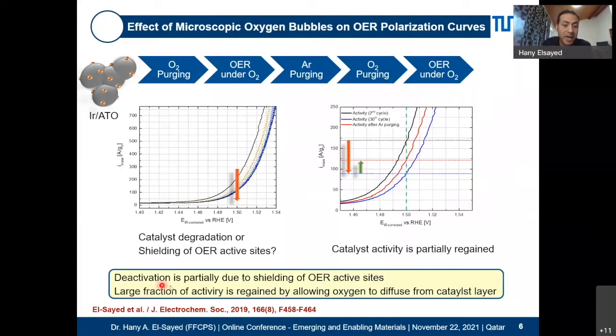Our conclusion is that the deactivation is at least partially due to shielding of oxygen evolution OER active sites. And a larger fraction of activity is regained by allowing oxygen to diffuse out of the catalyst layer by purging with argon. Well, that was the first experiment.